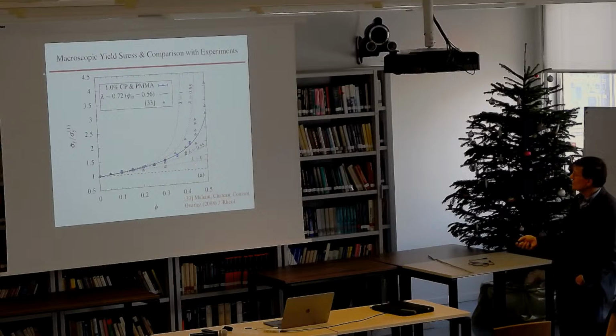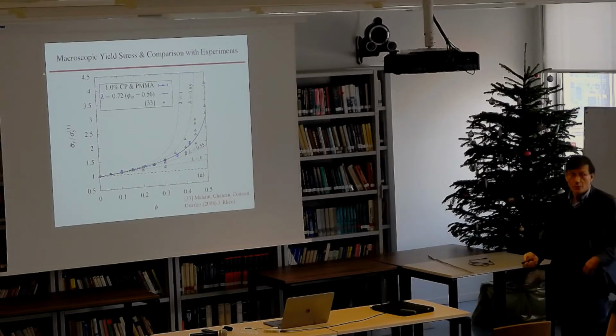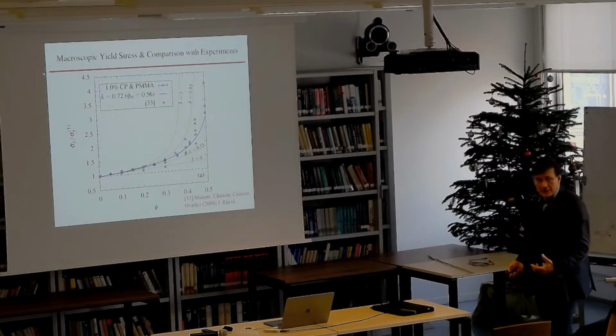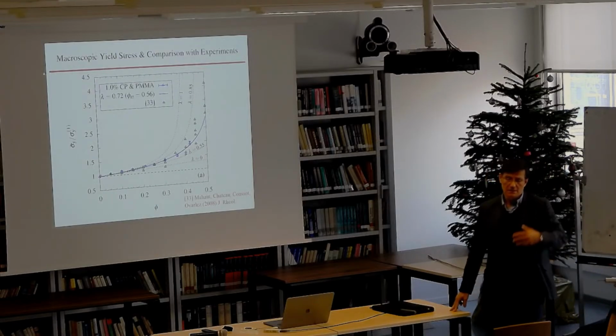This is the effective yield stress as a function of the volume fraction of particles. Again, you have the lower bound, the self-consistent, and then this blue line here with the same lambda as the Newtonian suspensions. Why? Because we use the same particles, and we assume that the distribution of particles would be the same.